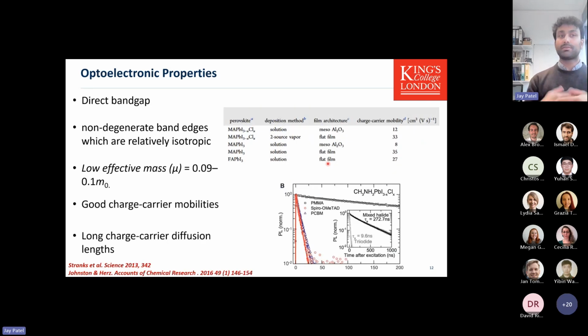And then it comes to the amount of traps. The material has shown that you can process it with very low temperature synthetic methods, and the traps that form, and traps are defects that occur on these crystal lattices, are essentially benign, where the charge carriers are not actually trapped. The charge carriers can actually diffuse to the electrodes, and you get a really high photocurrent and a high photovoltage. These are all important aspects in making a good photoabsorber.